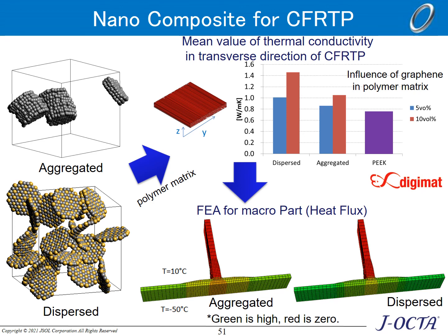We now use this structure to perform a finite element analysis of heat transfer. The results are not shown here. Next, we calculate the average thermal conductivity of the CFRP using the equivalent inclusion method. In the upper right figure, we evaluate the properties in the z direction. The obtained results are shown in the upper right graph. The dispersion of the graphene at the nanometer scale affects the average properties of CFRP at the micrometer scale.